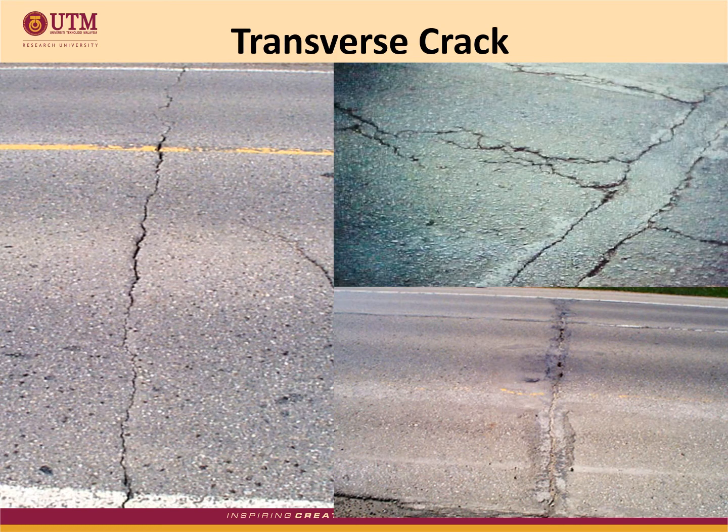Okay, next is the transverse crack, which are single cracks perpendicular to the pavement centerline. Transverse cracks can be caused by reflective cracking from the bottom layer, daily temperature cycles, and poor construction due to improper operation of the paver. For treatment, less severe cracks can be sealed to prevent water penetration, and more severe cracks should be fixed by removing the cracked layer and replacing it with an overlay.